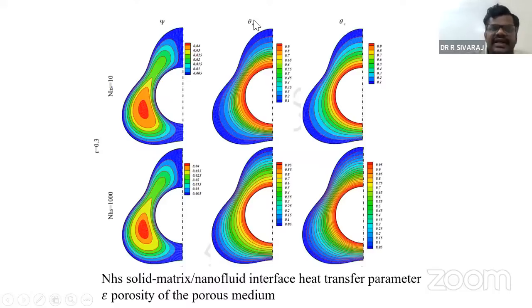In terms of the heat transfer of the fluid, if you see, red color is for the highest heat transfer and blue color for the lowest heat transfer. The heat transfer variation, you can see it is spread up to this region. But in this, the spread is getting reduced, shrinking. So increasing this interface heat transfer parameter reduces the fluid heat transfer. But in solids, initially it is less, and when we increase it, it is high.